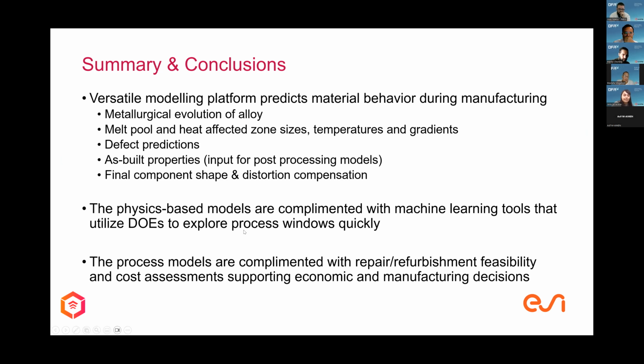Things I did not present in detail, just very quickly sometimes, is that the physics-based models do run several times to optimize a certain aspect. For example, if the melt pool is too large or if we see a lot of cracking, then we run a numerical design of experiment to see where to explore the different process windows. When we have such information, so 25, 30 simulations, we can run them through machine learning and explore the rest of the process window even quickly. So we complement the physics-based models with machine learning to get something we call the hybrid twin.